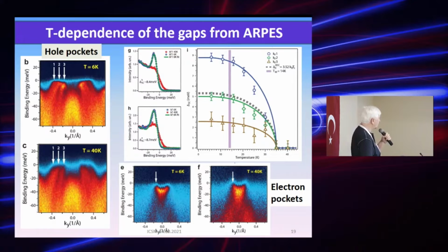There is nothing specific, like a BCS. And what we can conclude is that this superconducting picture indeed confirmed the four-band superconducting state in this material. And there is a large band. Mainly this superconducting condensate comes from the cylinders, from the hole band cylinders. So we do the same for electron pockets and nothing special. Basically, this picture confirms what can be found in 122 materials.